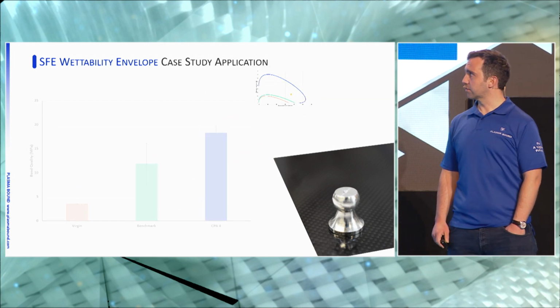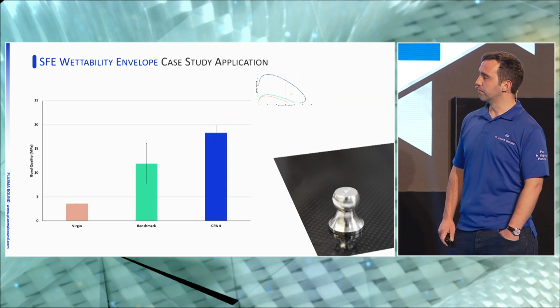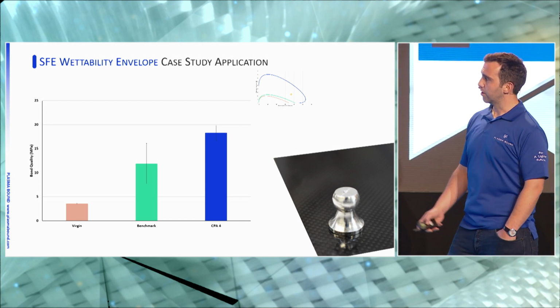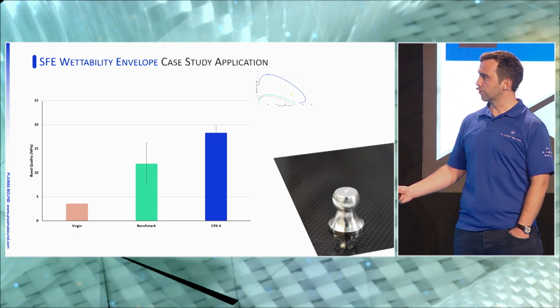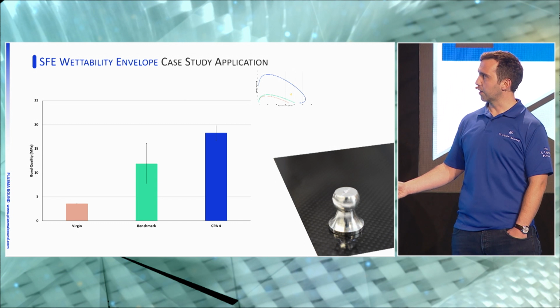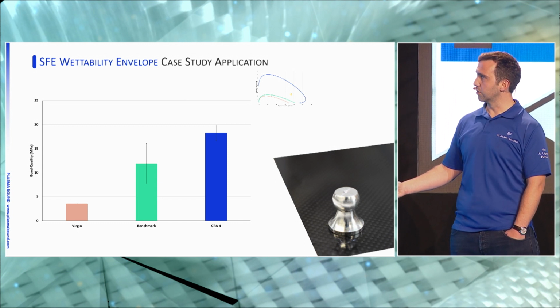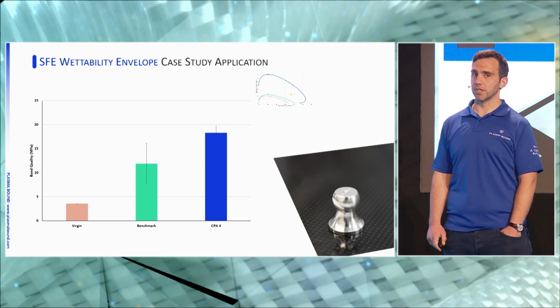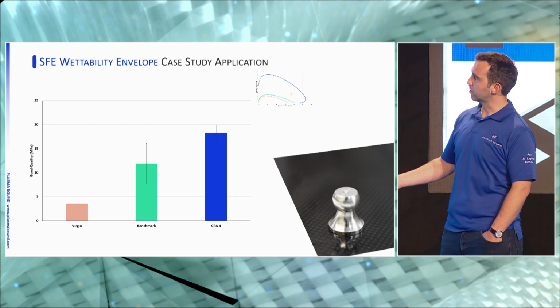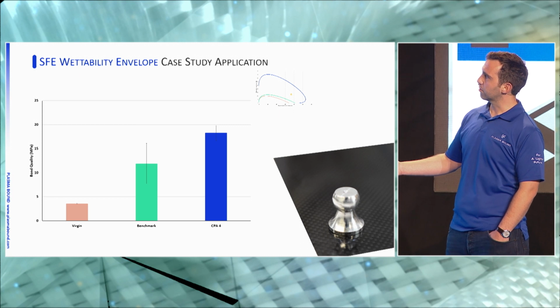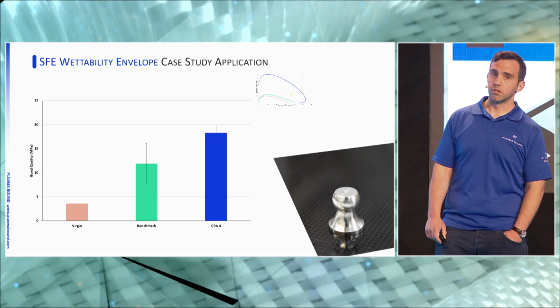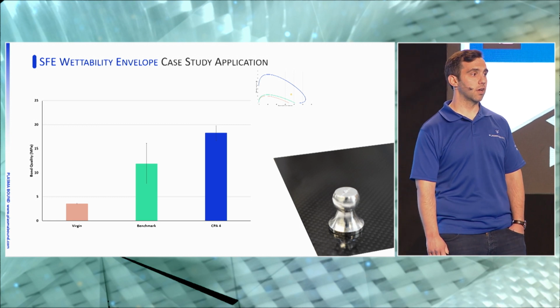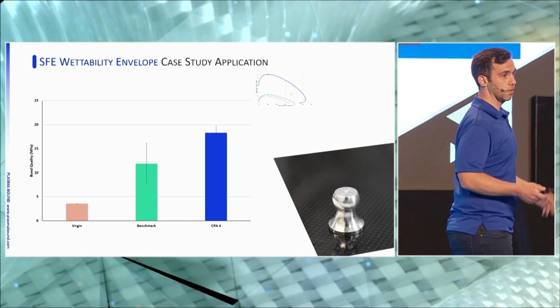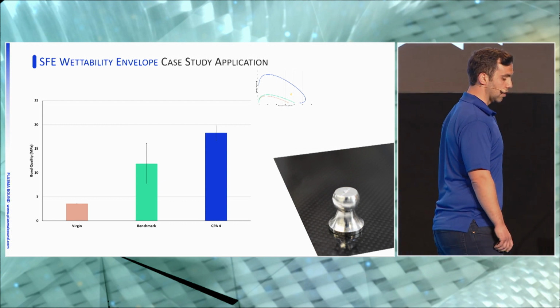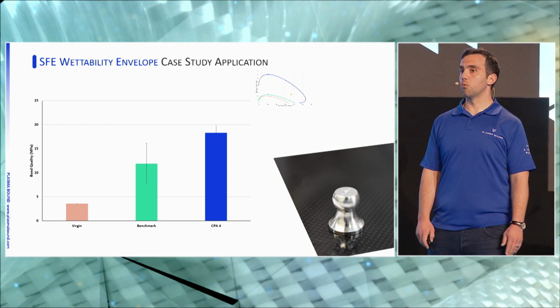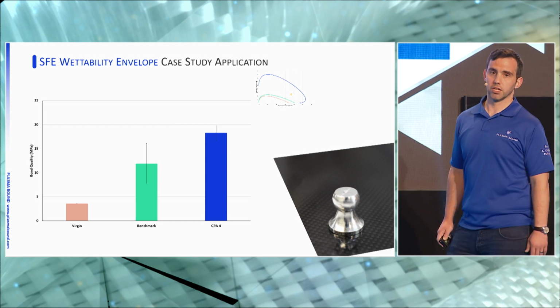This was demonstrated with real results. So we did pull-off tests internally and also did SLS testing for them. And the results, basically, you've got your virgin, which of course nobody was ever going to work with. This was their benchmark material, and I would like you to note the standard deviation, which was within a risk that they were happy to take at the time. And then if you look at the CPA prepared material, it is higher, and also the standard deviation is smaller, which means that now they have the opportunity to work in an operating window considerably outside of that of their original window. They could offer their customer a much better warranty and without any value change to them.